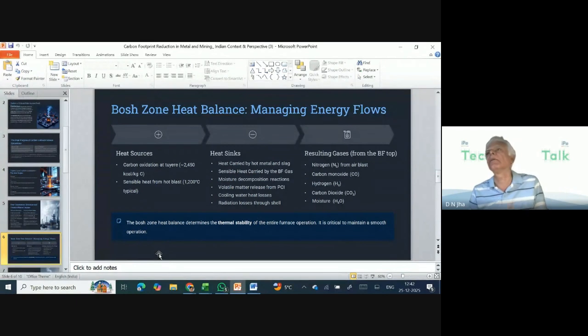So, I'll just give one example to prove this. Suppose I have to reduce the heating requirement. Let's say 40% of the heat goes along with the hot metal and slag. This is a rough number I gave; in some cases it may be 38%, in some cases it may be 43%, and so on. So if we have to reduce the heat requirement, then we reduce the slag rate. If I reduce the slag rate by, let's say, 10%, then the heat carrying capacity of the slag will come down.